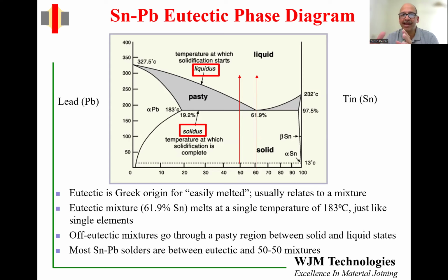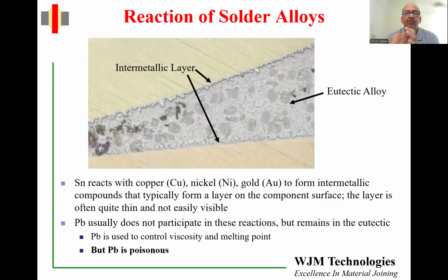Now, once the alloy melts, how does it react with these base metals? So let's look at that. Here I'm showing you a cross section of a solder bond where you have two components which have been joined, and you can see an intermetallic layer at the interface on both sides and a eutectic alloy which is filling the middle. So what happens is when you select a particular braze or solder composition, only some of the constituents of that composition will react with the base metal.